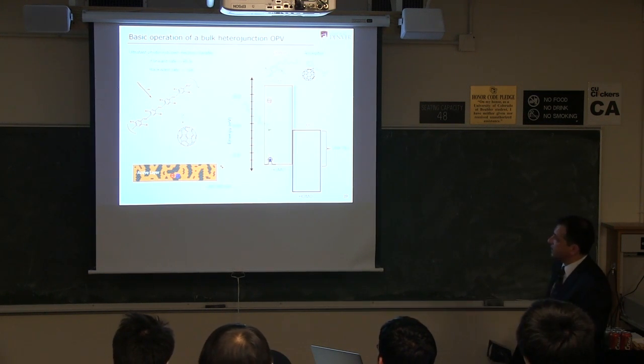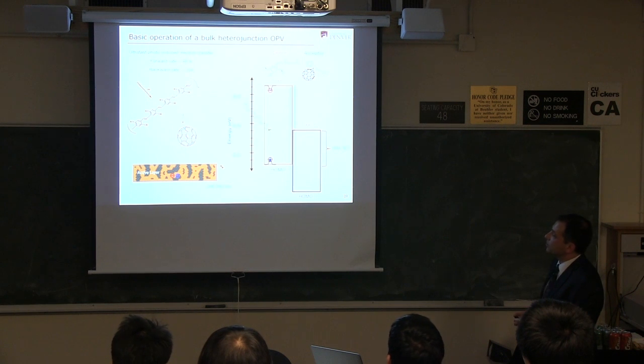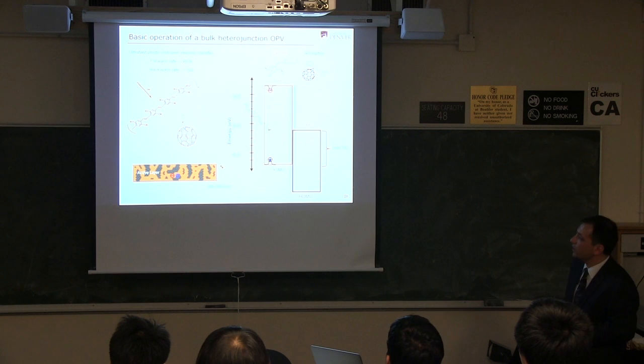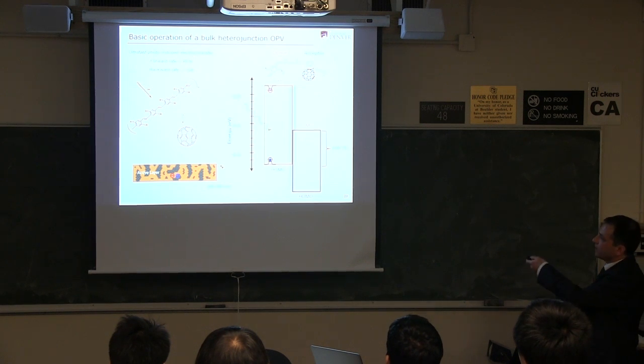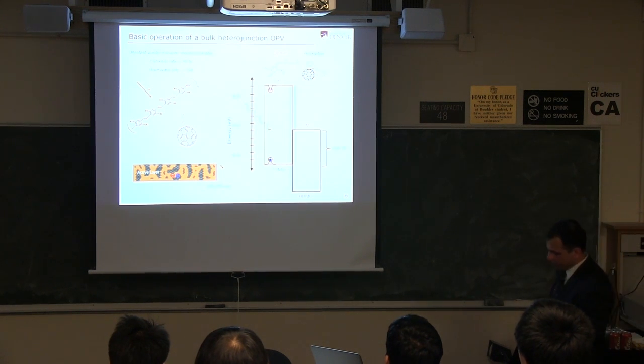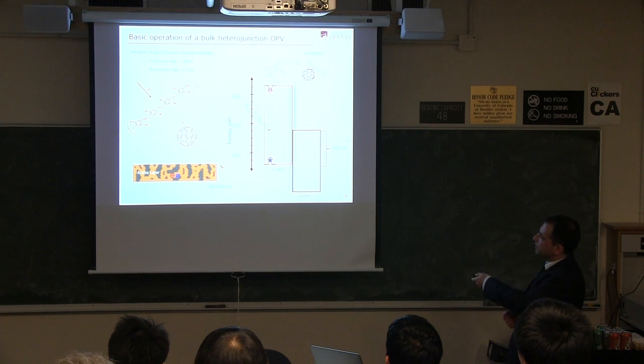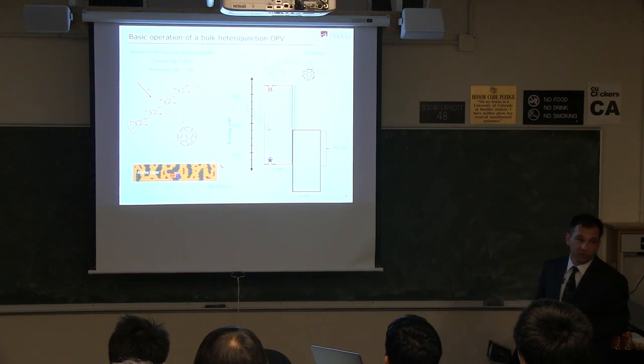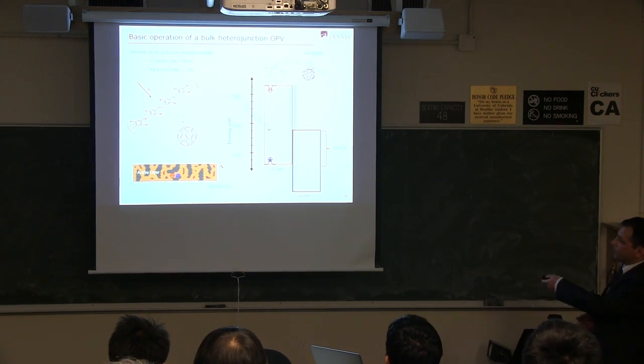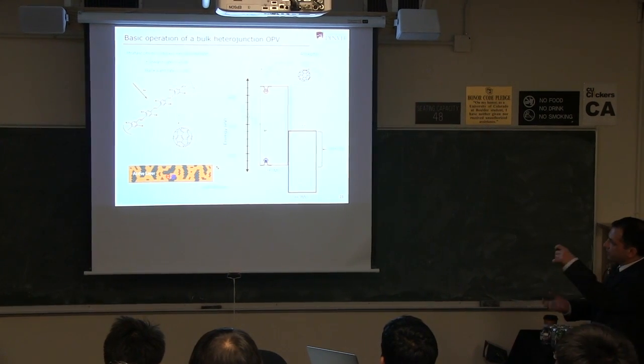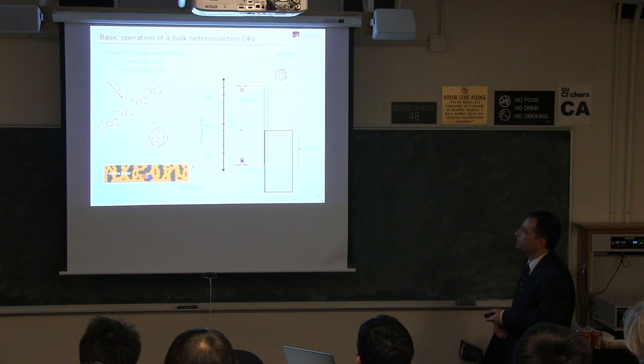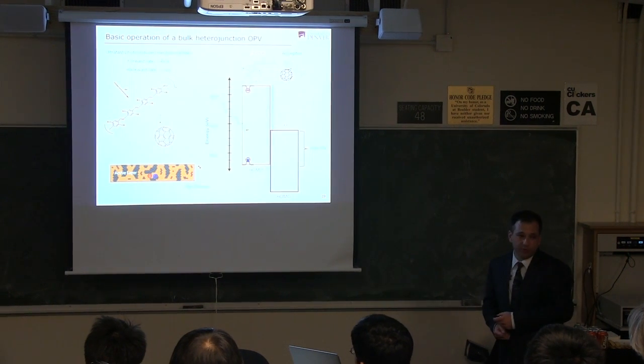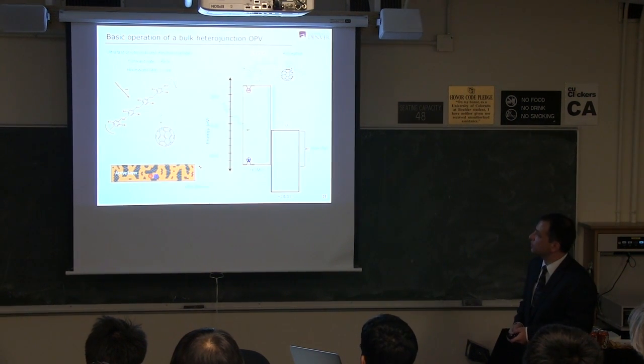So just schematically, if we look at the band structure of these things, we can draw HOMO and LUMO levels. That's basically chemists speak for valence band and conduction band. So we form an exciton on one of these materials. And the important point is that you don't create free charges right away. You've got a bound state where you see that the energy of the hole and the electron have collapsed in a little bit. That's the exciton. That has to diffuse or be created near the interface with the acceptor so that we can dissociate it.